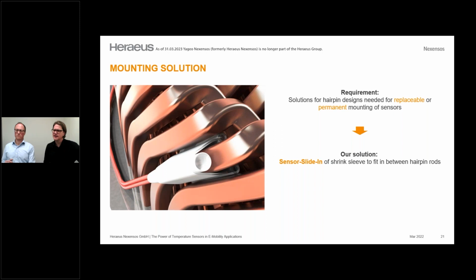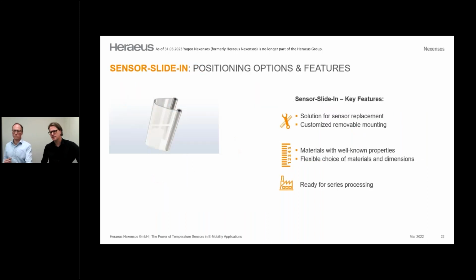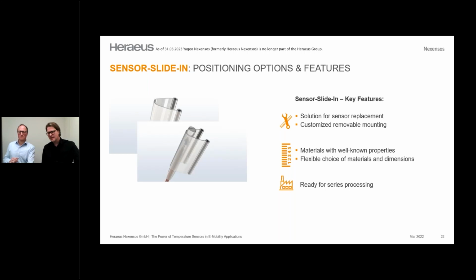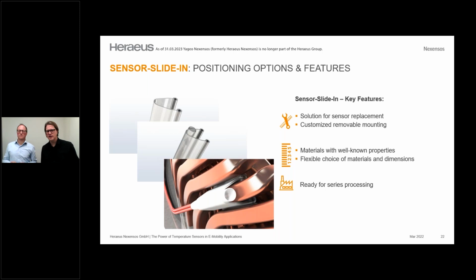We call it a slide-in sensor. How does that work? We take two rods or chopsticks, you can call it however you want, and put them into a shrinking tube at the end, as shown here. Then we fold the shrinking tube to a position like it's shown here, and between the gaps of a hairpin, we slide that complete system in. And in the end, once it's slid in, we take a heat gun and shrink the material for fixation directly on the hairpin.